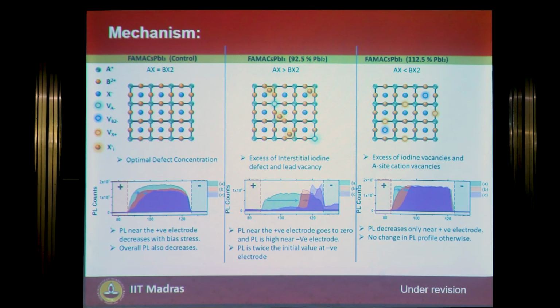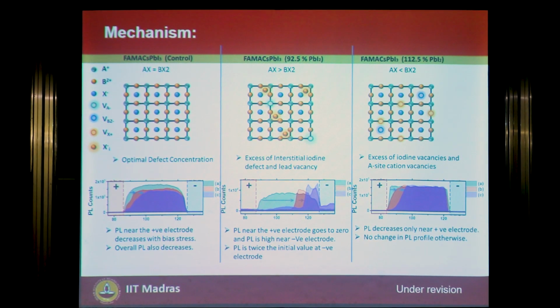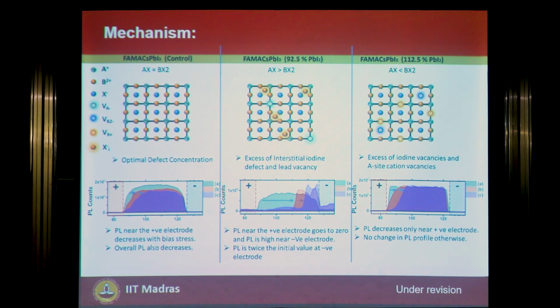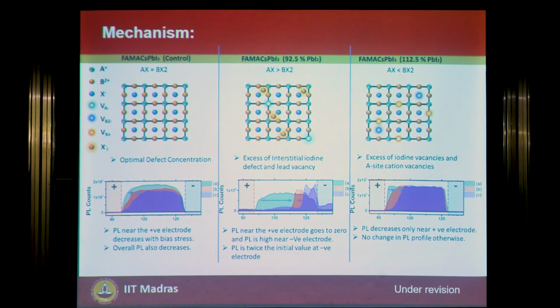It's all working basically unit cell wise, where we are trying to change the volume of the crystal itself and also the tilting of the octahedron. For example, if you consider only FA-based FAPbI3, it goes to the yellow phase. So if you want to keep it in the semiconducting black alpha phase, you have to add just like 5% of MA. So what is happening is you are trying to play with the unit cell of the perovskite, which keeps your structure.